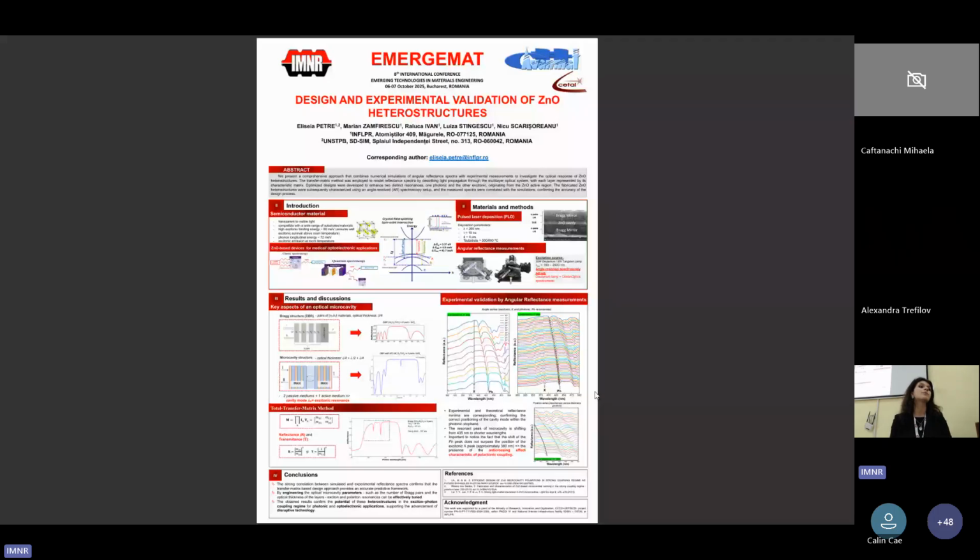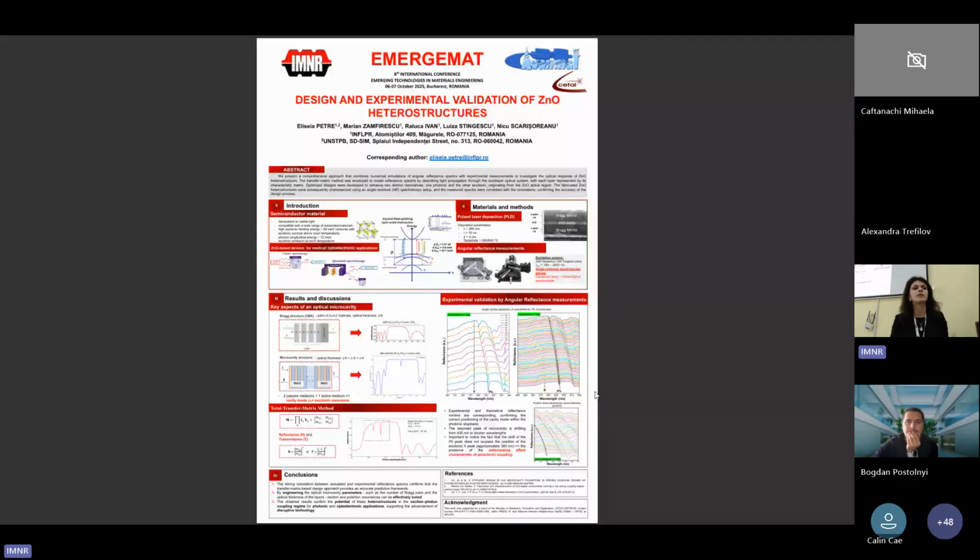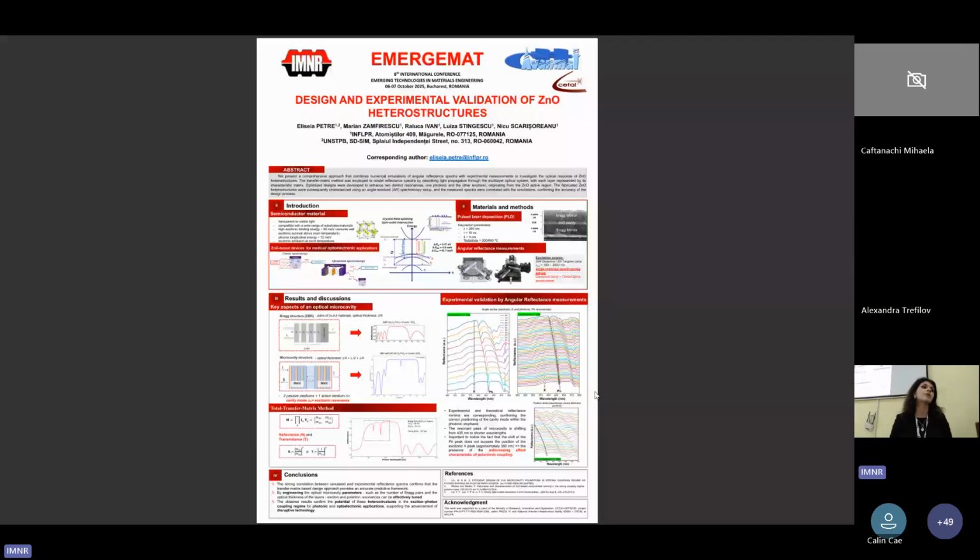And what is important to know is that we have 2 resonances, the photonic one at approximately 400, and the excitonic one, which is specific to the material. As the angle of incidence increase, they are shifting to shorter wavelengths, but the photonic peak does not surpass the excitonic position. So this is a sign of anti-crossing effect. It's a sign of strong light-matter coupling.